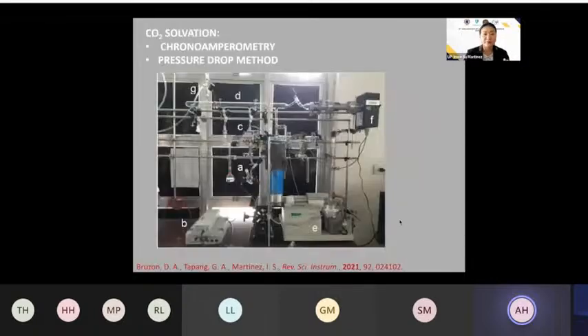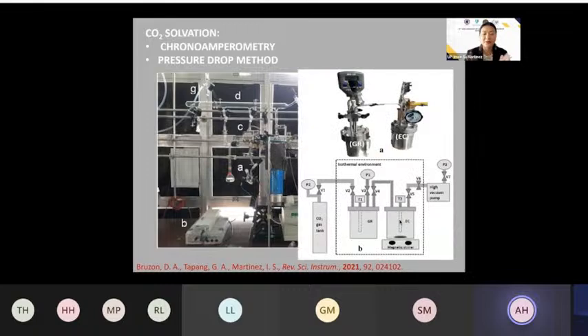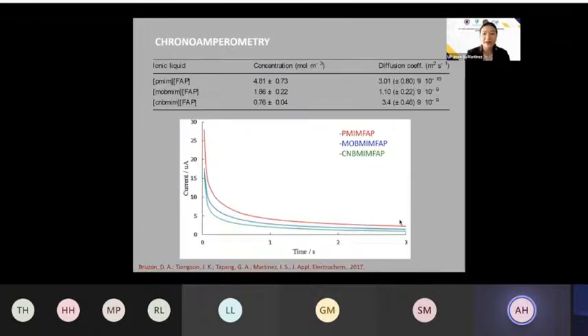And then using the same setup, our vacuum line, we perform controlled chronoamperometry to determine the amount of dissolved carbon dioxide in our ionic liquids. So to determine the amounts of carbon dioxide, we actually do 2 techniques. One is chronoamperometry, and the second one, which is the more acceptable technique, is called the pressure drop method. And as you can see here, we've actually built most of the instruments in our lab. And these are our results.